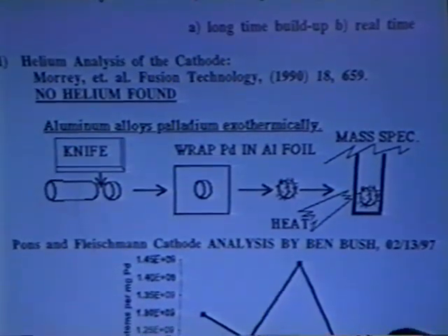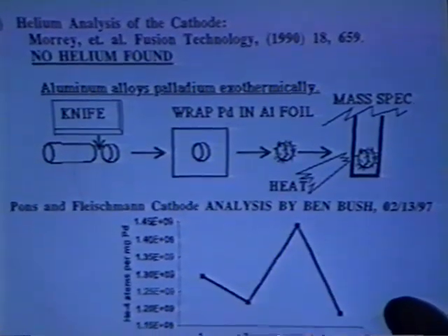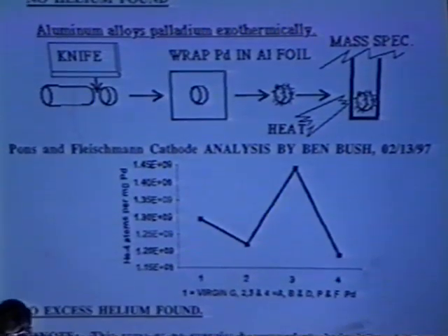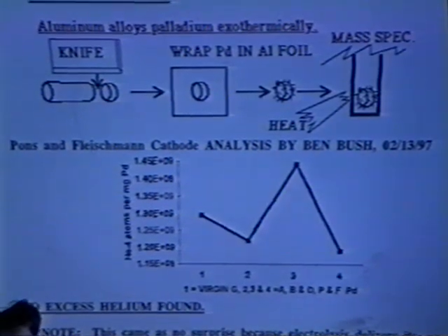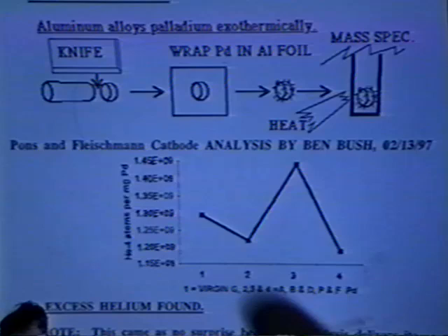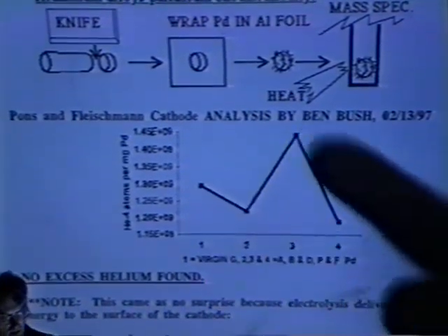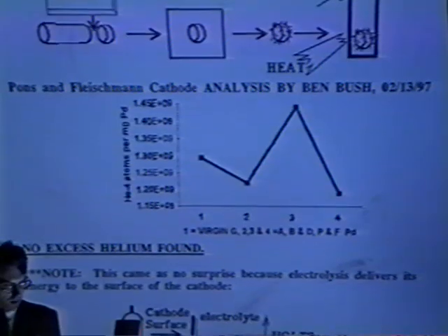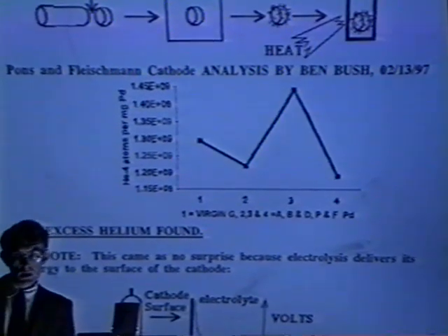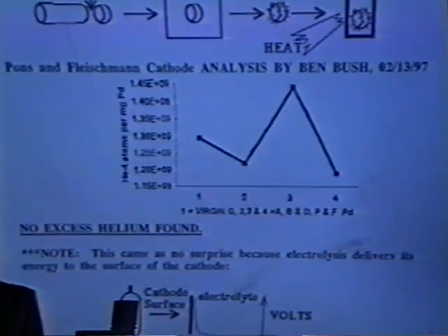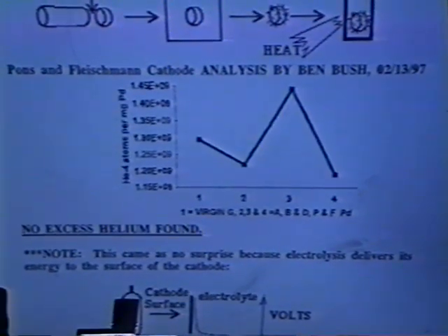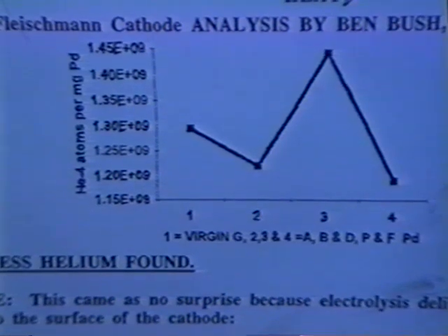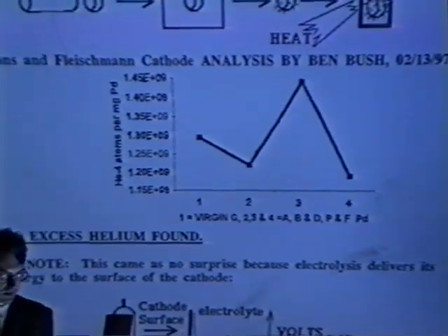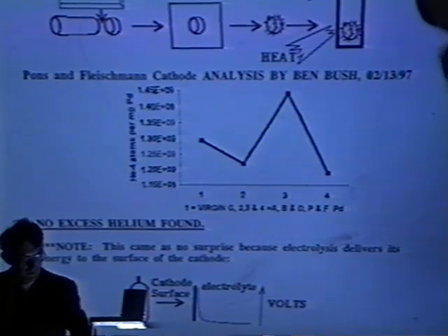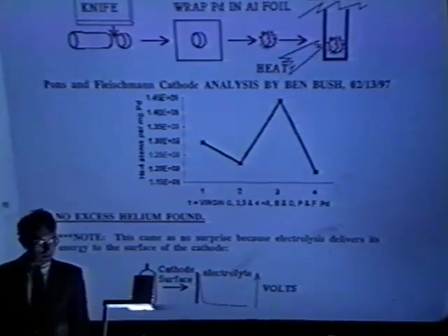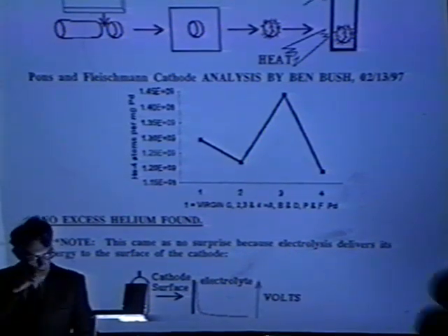Now I did this, for example, with some cathode materials versus a piece of virgin palladium from the same lot as the cathodes were made. That was the virgin piece, and here are the 3 cathodes. And I would call that no helium found, and the helium-3, helium-4 isotope ratios were about that error. So what I'm saying is you're not going to find helium if you look in the cathodes, and that's what Morrey found way back when. Back in 1990, no helium in the metal.